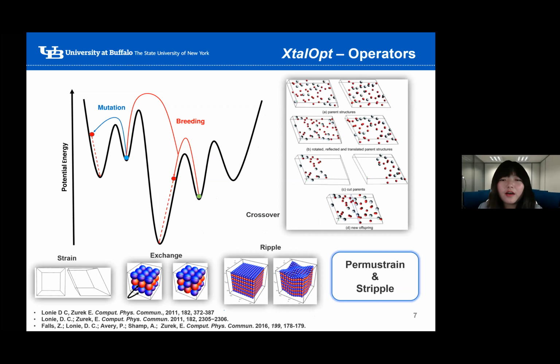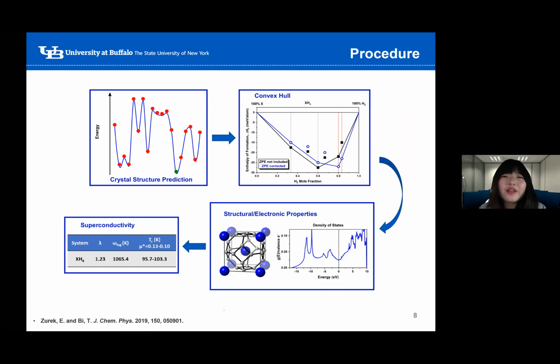So this page lists the operators used in XtalOpt, including crossover, strain, exchange, and ripple. The combination of strain and exchange creates permustrain, and stripple is strain plus ripple. This flow chart is an overview of the procedure we use in our computational works. For example, we start from the crystal structure prediction to explore the potential energy surface using XtalOpt for certain stoichiometry at a chosen pressure.